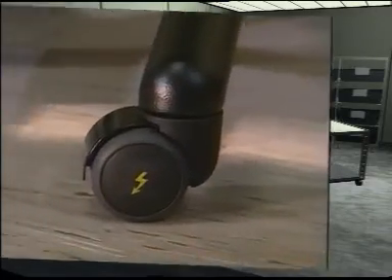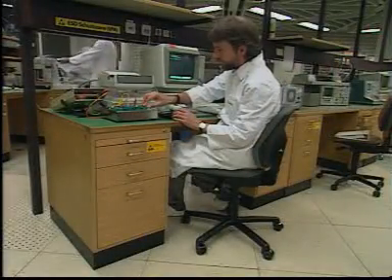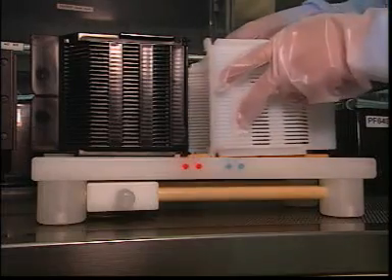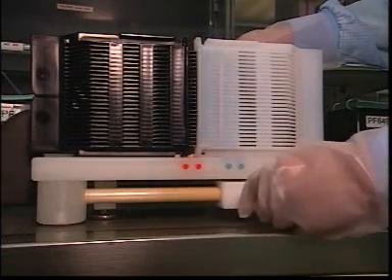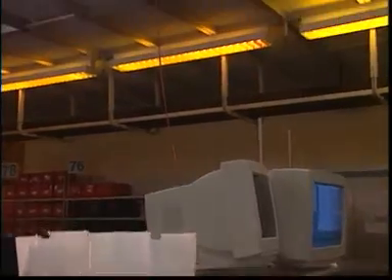Moveable storage equipment is also fitted with groundable wheels. The same principle applies to chair wheels — the covers and upholstery are also made of dissipative materials. The use of highly chargeable insulated materials, especially in clean rooms, is often unavoidable for process reasons. They can be neutralized not by grounding, but rather only through the use of an ionizer.